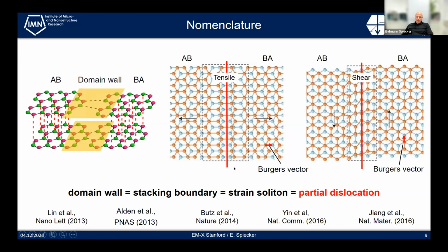So there's one peculiarity of dislocations in bilayer graphene, that all the dislocations are partial dislocations, which means that the Burgers vector is not a lattice translation. So you make a stacking fault, because the stacking fault has no energy, because AB and BA is equivalent. There's no need to make a perfect dislocation. So all this together can be described by the concept of dislocations, and in particular partial dislocations.